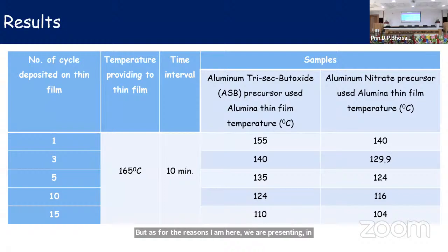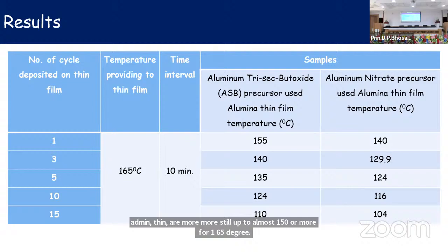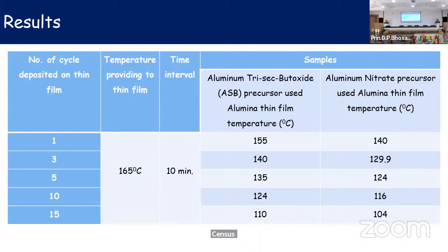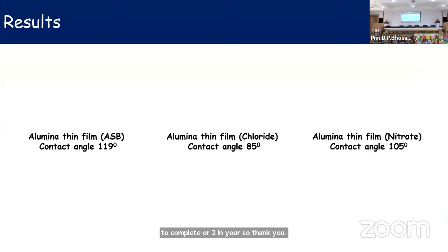The aluminum alkoxide based precursor alumina thin film is more stable, up to almost 150 or almost 165 degrees Celsius. To conclude, we went through using the simple hot plate method and IR camera images to observe these results. So thank you. And there are some contact angle results. The aluminum alkoxide precursor shows 119 degrees, and thin films made using aluminum salt based precursors have a lower contact angle.